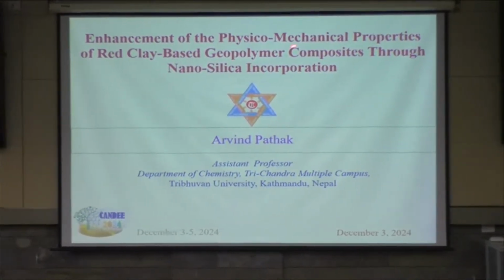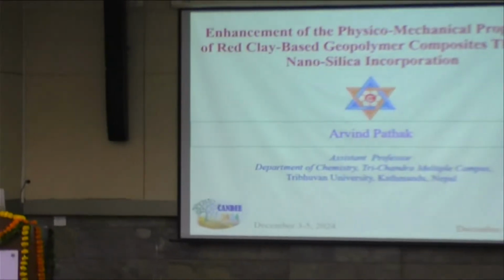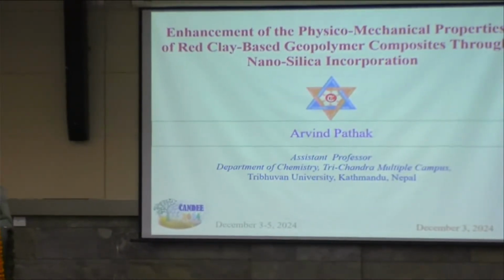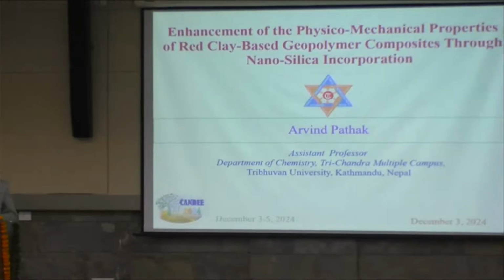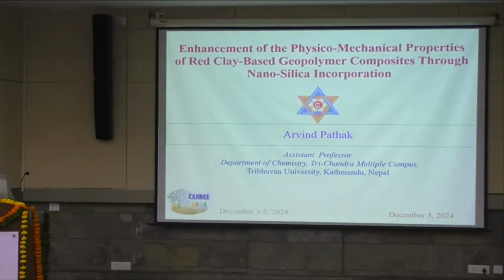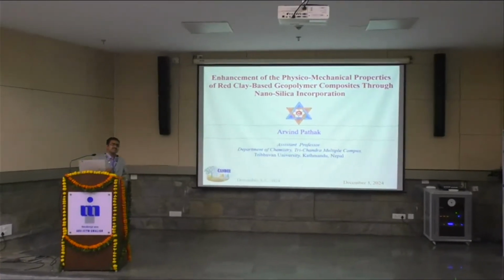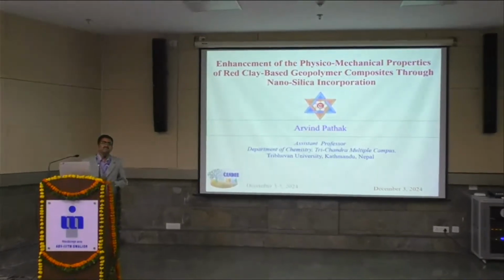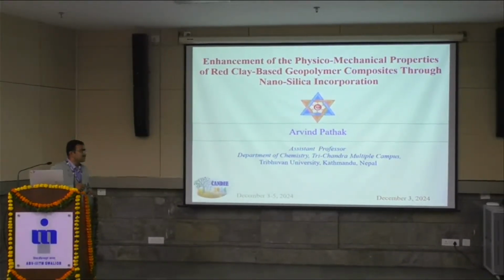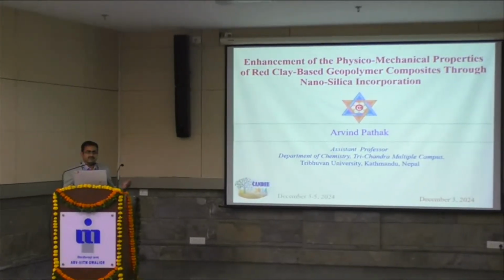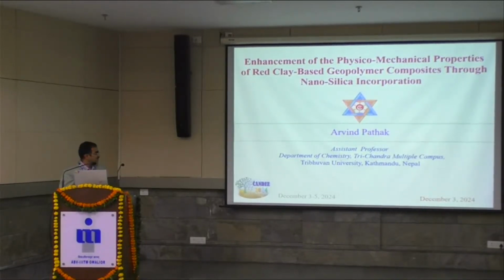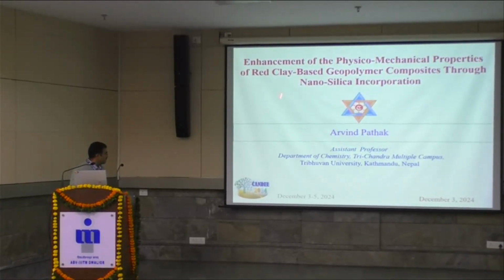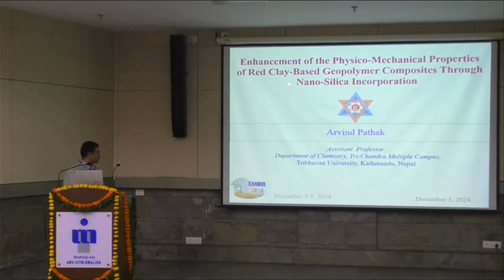Actually, geopolymer has been applied for transformation of waste materials such as slag, fly ash, as well as the clay materials such as metakaolin, kaolin, red clay, as well as red mud, etc. We found that in this study, we have introduced the nanosilica for the enhancement of physico-mechanical properties of the geopolymer.